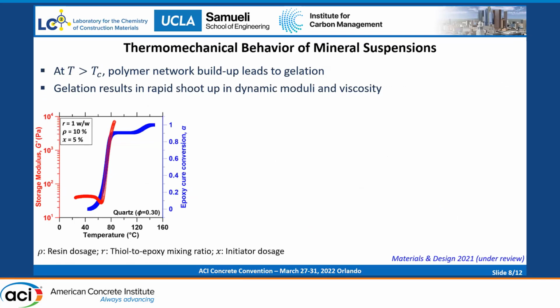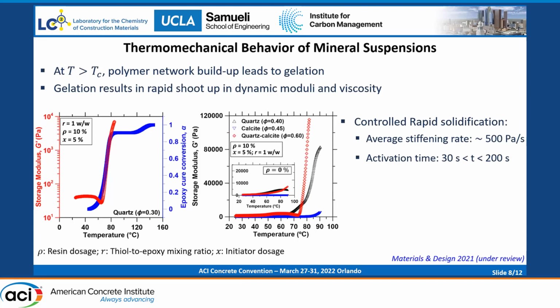Coming to some results on these mineral suspensions, what you see here is a one-to-one correspondence between the progress of the curing reaction and the stiffening, where the stiffness evolution that we measured using a rheometer is compared with the cure conversion that is procured from the DSC analysis. So as you can see, we get a rapid increase in the elastic modulus once we achieve a threshold cure conversion within the resin. What is shown here is the real thermoresponsiveness in these suspensions for different suspensions: quartz, calcite, and a mixture of quartz and calcite.